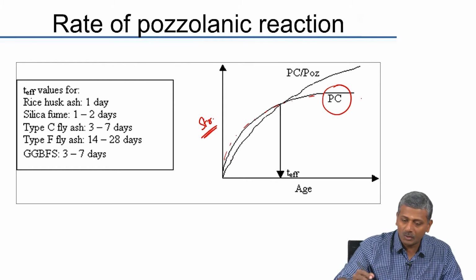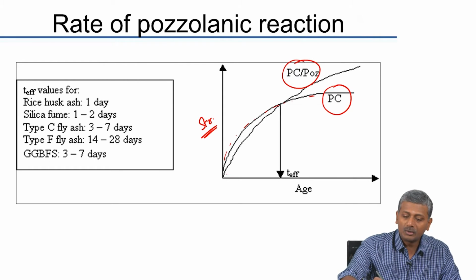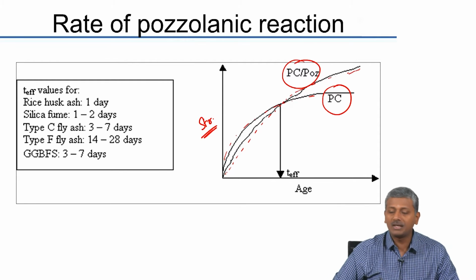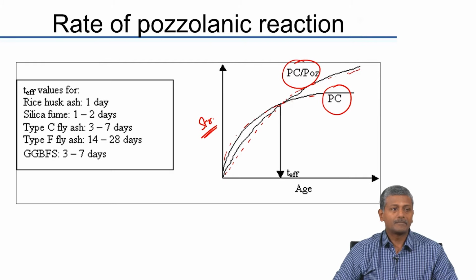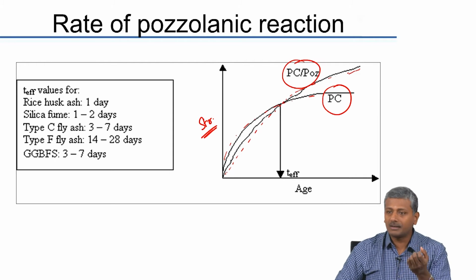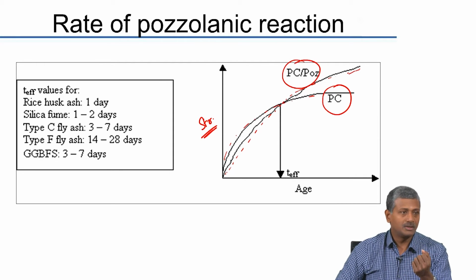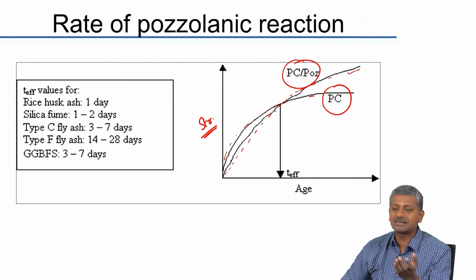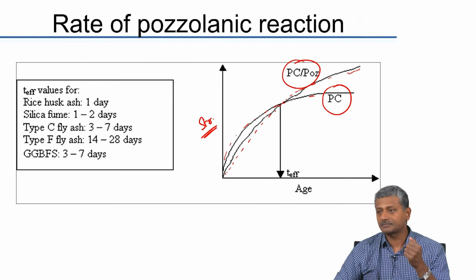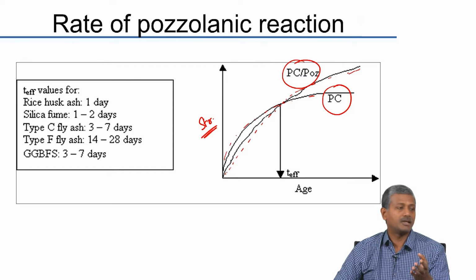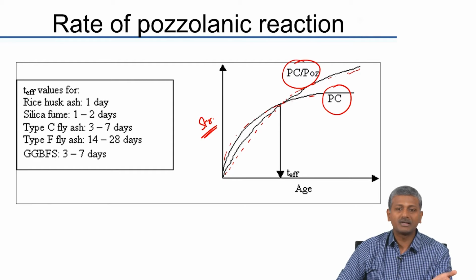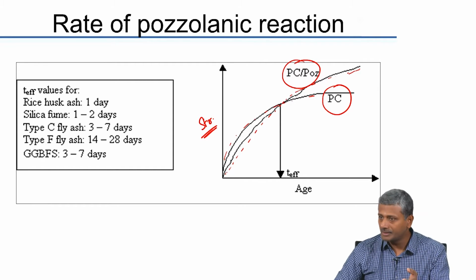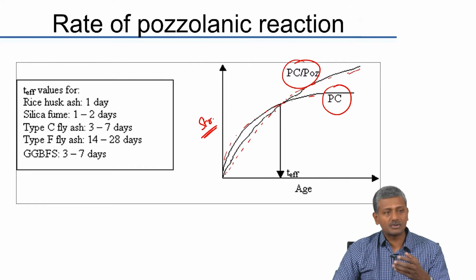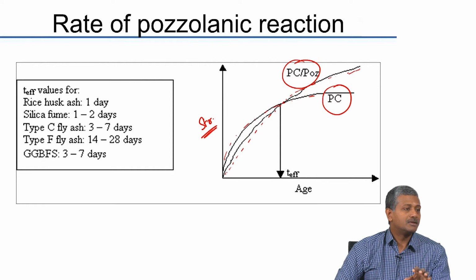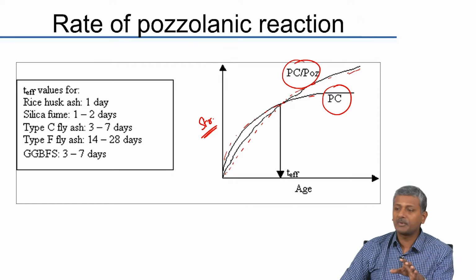Now, assuming that is the case, when you have a Portland cement pozzolan system, you have a strength development rate which is slow in the beginning, but eventually has the potential of overtaking your Portland cement system, and that is simply because the hydrates that are forming as a result of the pozzolanic reaction have a better volume filling ability as compared to the products of Portland cement itself. So, the more volume you fill up, the less porosity you have, the greater strength you will have. Potentially, I say potentially because you are assuming that there is sufficient moisture available and sufficient curing being done for these systems.